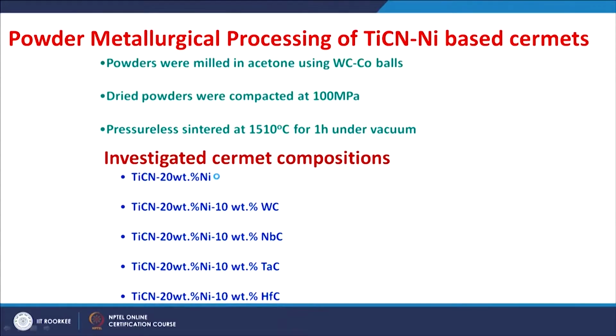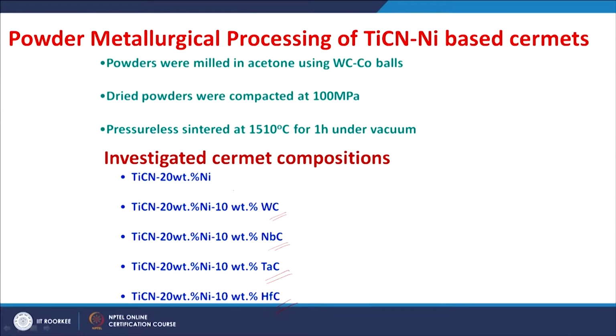For this, cermet materials were prepared by a powder metallurgical processing route. Initially, the powders of titanium carbonitride and nickel, and then respective carbides of tungsten carbide, niobium carbide, tantalum carbide or hafnium carbide were mixed in a ball mill using tungsten carbide cobalt balls in acetone. These were compacted at 100 MPa, and then these compacts were sintered in a conventional way, pressureless sintering at 1510 Celsius for 1 hour under vacuum. So, these are the investigated cermet compositions: TiCN with 20% nickel, and TiCN with 20% nickel with 10% tungsten carbide, or 10% niobium carbide, or 10% tantalum carbide, or 10% hafnium carbide. So, these cermets were studied.